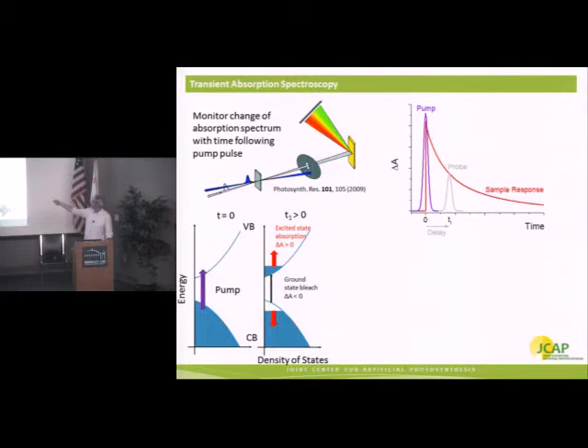So here, on the top we see time, our pump comes in at time 0. If we now interrogate it at a time t1 after the pump comes, well, we have now no electrons at the conduction band edge of the material. That means it's going to absorb less light at the band gap of the material. So you'll have a negative going transient absorption, or a bleach, as we call it. You also have absorption related to the excited states. So these electrons and holes that are now in excited states can absorb, whereas they couldn't when they were in the ground state. So we have additional positive transient absorption signals that we can observe.